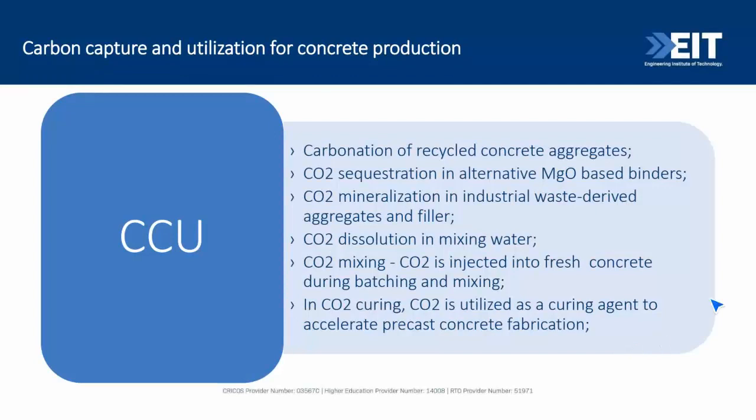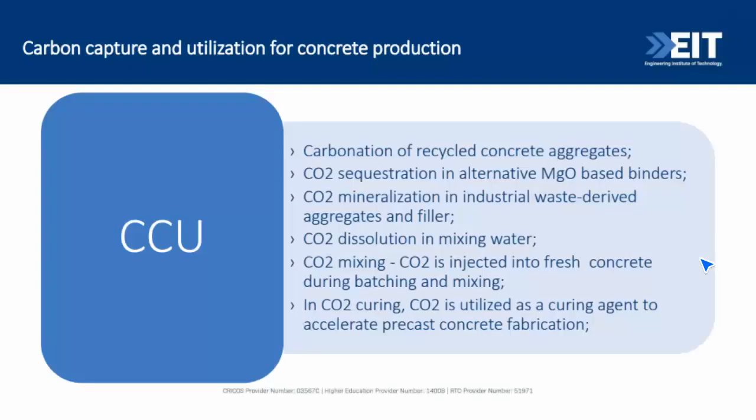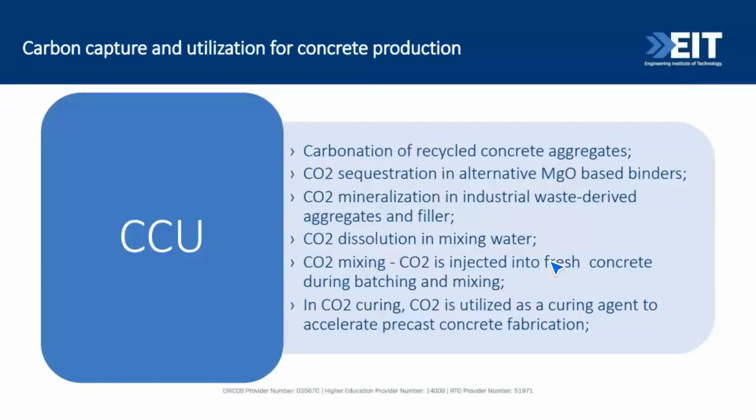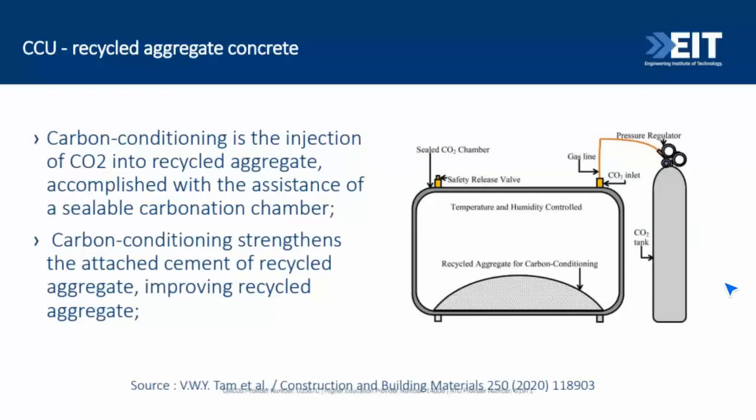When you have the carbonation of cementitious materials, researchers are saying that it's a very attractive option to reduce the environmental costs of concrete production. First of all, when you have the carbonation of cementitious materials like fly ash or slag, it can strengthen the cementitious materials and also reduce the use of pure clinker, the pure Portland cement. And the second alternative is to absorb and sequester carbon dioxide. So let's have a look into some of these alternatives in detail. And I will start with